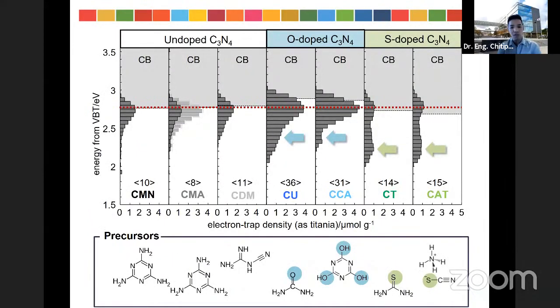So here is shown the ERDT pattern, which is the result obtained from the DR-PAS technique. And it's clear that the oxygen and the sulfur-doped graphitic carbon nitride show a new electronic state level around 2.2 electron volts, at the point indicated by the blue arrow and the green arrow. The generation of the new electronic state can trap the electron and reduce the energy band gap to enhance the photocatalytic performance and enhance the optical property in the visible light region.